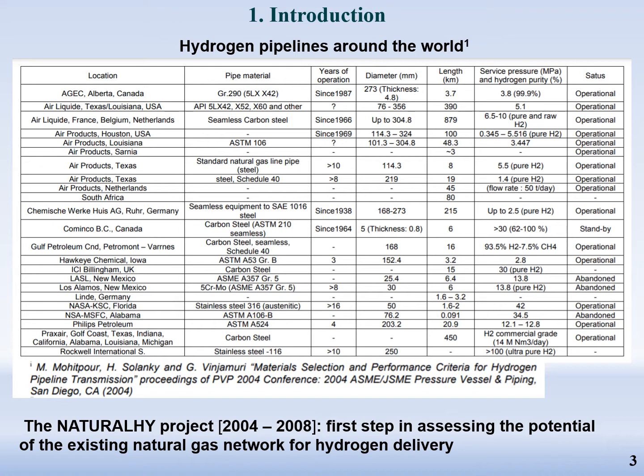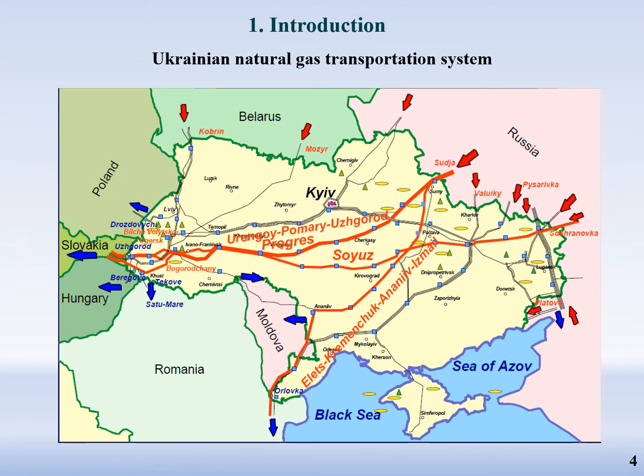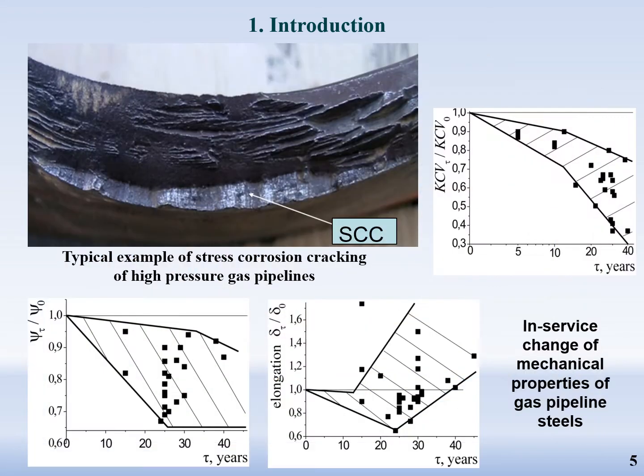The NATURALHY project is the first step in assessing the potential of the existing natural gas network for hydrogen delivery. Ukraine has an extended network of natural gas transit pipelines that could be used for supplying hydrogen as well. However, during long-term service, pipeline steels can degrade. A significant decrease of mechanical properties of operated steels, mostly brittle fracture resistance, can finally cause structure failure.